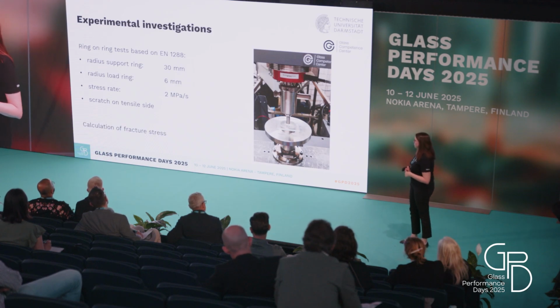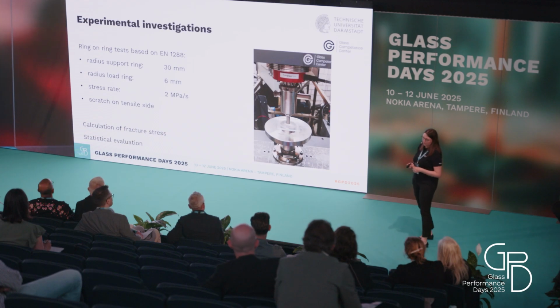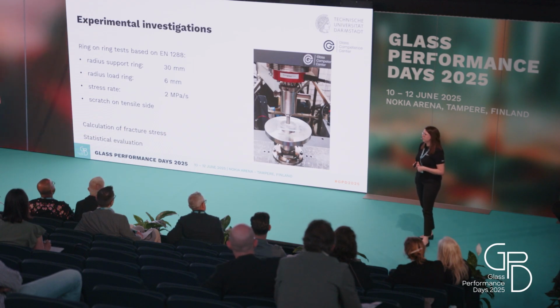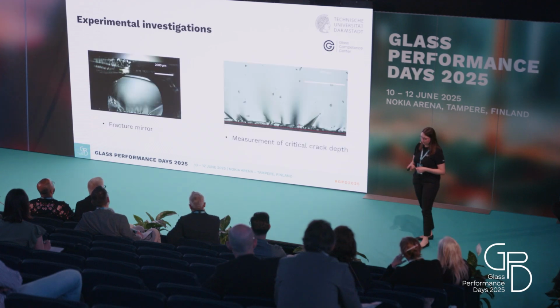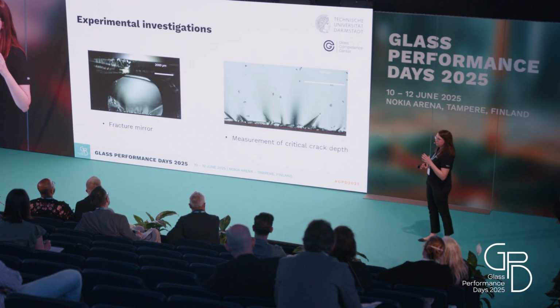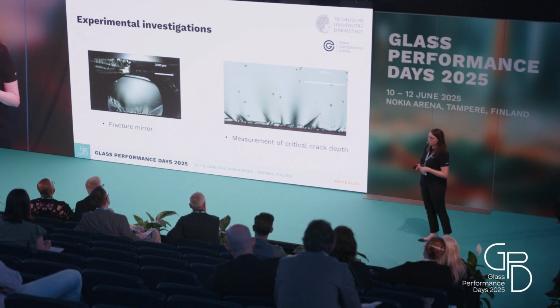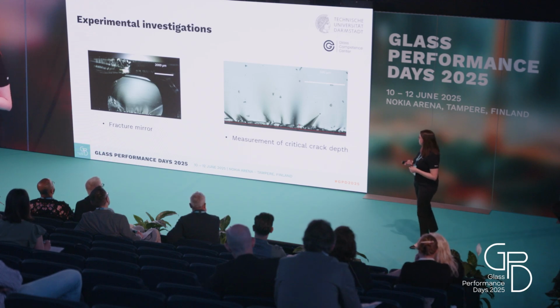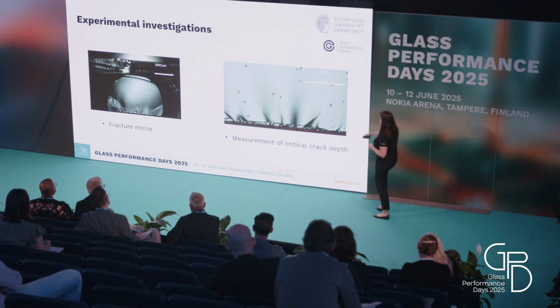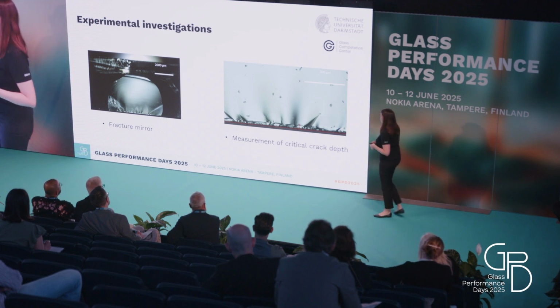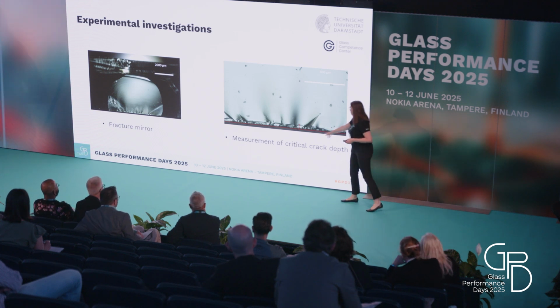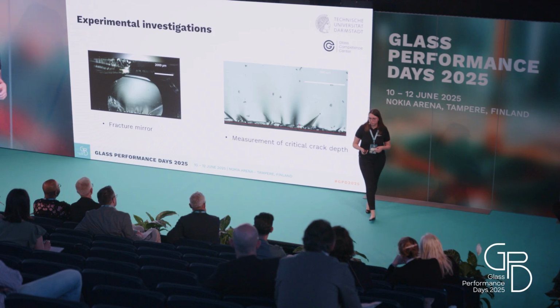From the fracture force, we calculated the fracture stress, and then we did a statistical evaluation with a two-parametric Weibull distribution function. After the ring-on-ring test, we looked at the fragments and searched for the fracture mirror. Then we zoomed in. So this is a zoom from the other picture, and then we measured the critical crack depth with the microscopy.